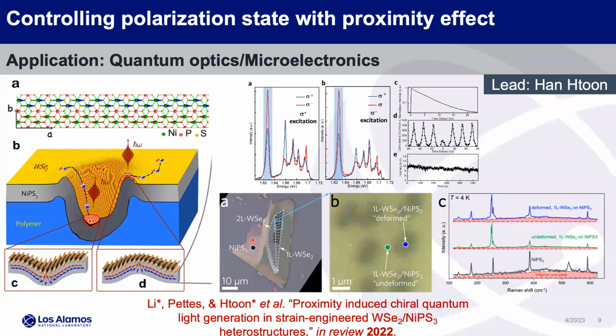We got NiPS3, exfoliated it, exfoliated tungsten diselenide on top of this, monolayer tungsten diselenide. And then one of our staff members who's really good at atomic force microscopy punched this with an AFM tip. So you're creating an inverse trench shape, and you'll have the same kind of bending strain within this defect structure.